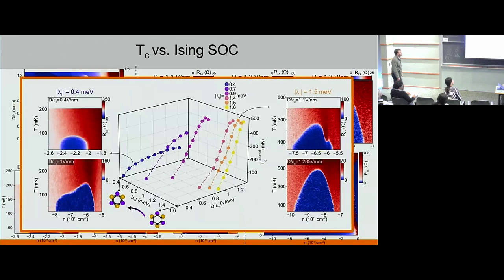And now you can summarize this for all the devices in a 3D plot, where you have displacement, you have strength of spin-orbit coupling, and you have optimal TC, optimal both in displacement and density. And then you can see the behavior of all of these devices. So essentially, if you have a low spin-orbit coupling, your graph looks like this. It's onset very early, but then it's saturated in TC. And the other ones onset much later, but they also reach higher TC. All right?